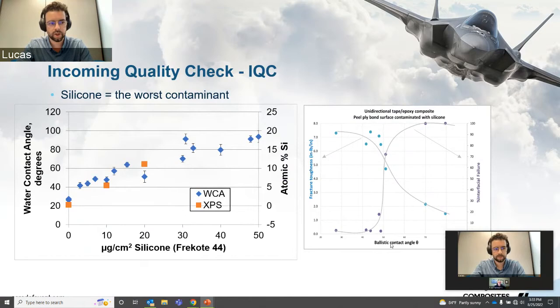The chart here on the left shows our water contact angle on the left axis, the amount of silicone that we're applying to composite samples on the bottom axis, and the atomic percent silicone on the right axis. What you can see here is once we get to 10 micrograms per square centimeter, we're up above 40 degrees. Typically, when we see real problems with adhesion in most applications, it's when you're in this range of 30 to 40 micrograms per square centimeter, and you're right in that 80-degree water contact angle range. That's an immediate flag. If we're doing some problem solving and we see an 80-degree surface and there's been some intermittent failure, time out. Let's take a deeper look at that.